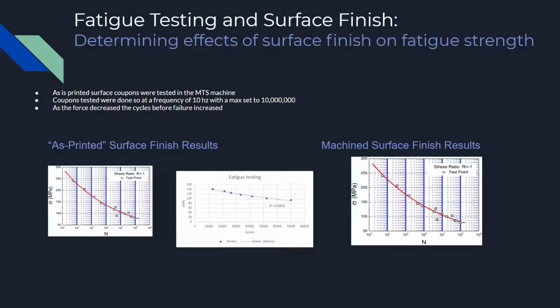As-printed surface coupons were tested on an MTS machine, with the frequency of the machine set to 10 Hertz. In testing the aluminum 6061 coupons, tests showed that as the ultimate stress force decreased, the cycles increased. Stress was decreased at a rate of 5% UTS per test, and results fell within a reasonable curve that is similar to non-3D printed manufactured aluminum.